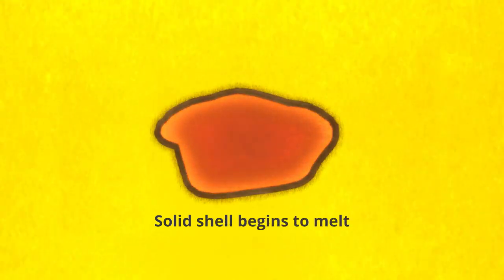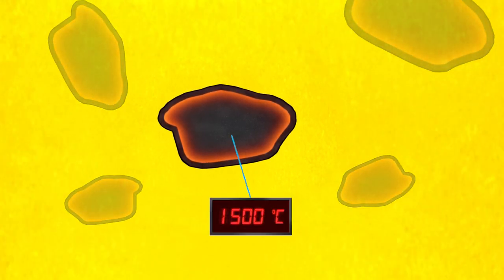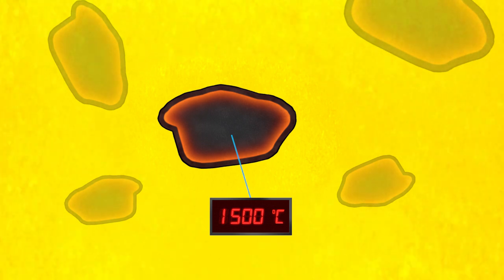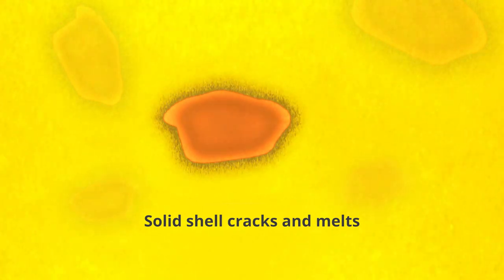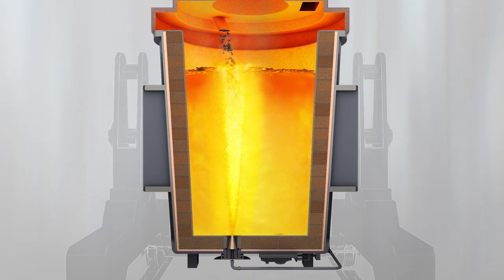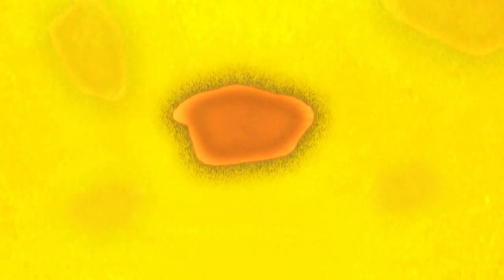This shell gradually thickens until the temperature equals that of the steel's liquidus temperature, at which point the shell begins to remelt. However, in the meantime, the core of the ferro-niobium particles will have reached a temperature above 1500 degrees centigrade and it interacts with the steel from the shell and starts to melt. The shell and core continue to melt, and the process is accelerated by vigorous stirring and careful control of temperature. The process repeats itself as the unreacted core material is uncovered.